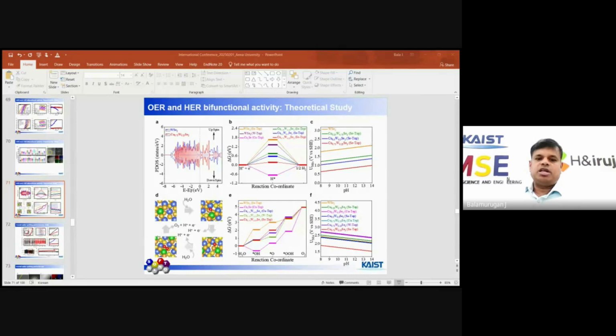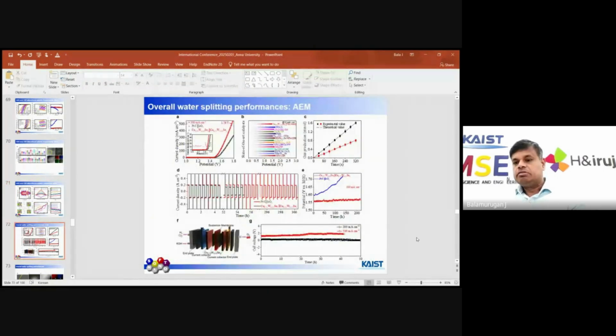So we also studied the mechanisms by DFT calculations. You can see how oxygen is adsorbed and how it is released during the oxygen evolution reaction. Finally, we made the device. You can see the lower onset potential, cell potential, and even at higher current there is lower potential. We also compared with the commercial catalyst, and with the theoretical and experimental values of hydrogen and oxygen evolution. For oxygen evolution, we calculated at 80, 160, 240, 320 seconds. And we do the reversibility test.